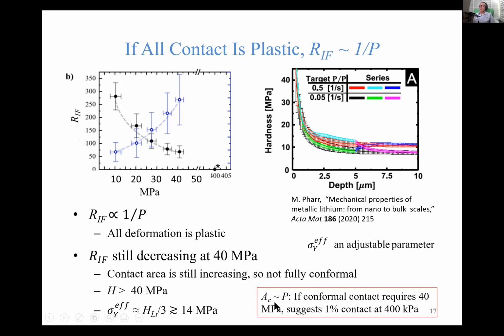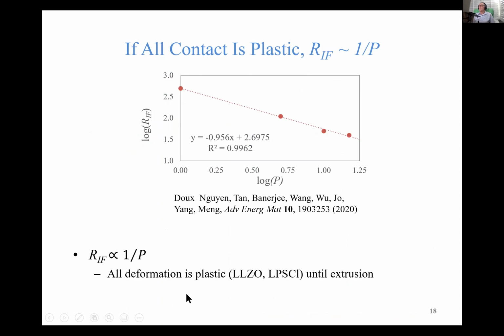Interestingly, the contact area scales with pressure, we showed. Now, if conformal contact requires 40 megapascals, that means if you're at 4 atmospheres, you only have 1% contact. So when you think about contact between lithium and a solid electrolyte under modest pressures, it's almost all not in contact. Now, that data was for LLZO.